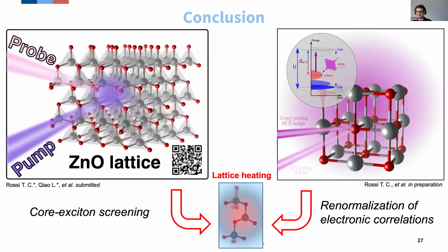So whatever is the experiment you have the most interest in, the zinc oxide or the nickel oxide, what these two experiments have in common is that when you do these pump probe measurements at synchrotrons, most of what you see is actually lattice heating. But once you have accounted for this effect, then what remains, that is the non-thermal part of the signal, is actually very interesting. So the core exciton screening that we highlighted in zinc oxide and the renormalization of electronic correlations in nickel oxide.